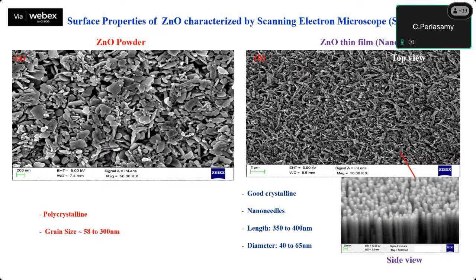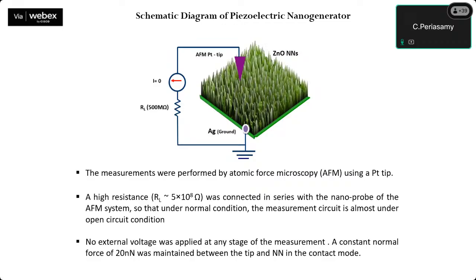This is the corresponding SEM image of the prepared nanostructures. From this SEM image, one can easily conclude that the fabricated zinc oxide thin film is in the form of nano needles. These nano needles can be used for different applications. Here, for example, is how one can use this nanostructure for energy harvesting applications.